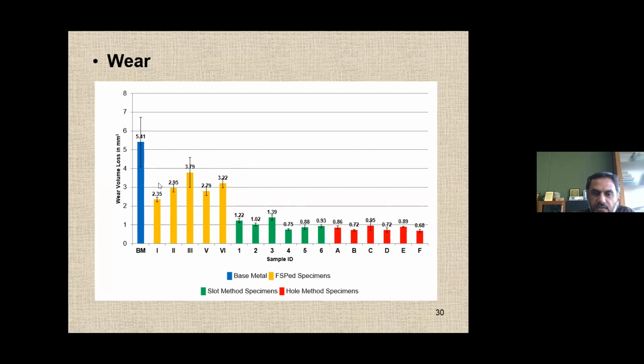And you see the FSP regions also, there was no reinforcement. And this is your parent metal wear, right? So wear volume in terms of millimeter cube. You see the parent metal wear is very high, close to 5.81. And if you just process it without any addition of reinforcement, you see there is a drastic reduction, because that indicates there is a good amount of refinement in the microstructure and the precipitates also.